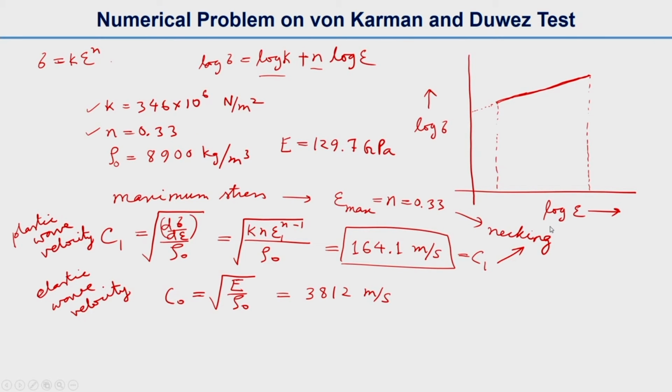So for the first part, epsilon 1, we have from our earlier equation that we already derived, so I am not going to write it differently. We put in directly rho naught V1 squared, (n plus 1) squared over 4 kn, to the power 1 over n plus 1.